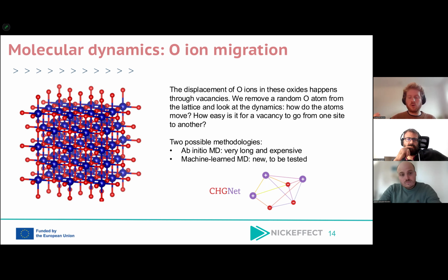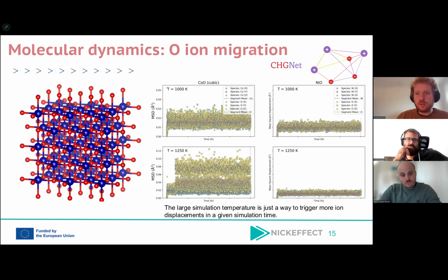Now there are many, many more different kinds of models. But so in CHGNet and in these other machine learning interatomic potentials, the forces are predicted using a machine learning model, and this model has been trained on DFT data. And so it's supposed to achieve close to DFT level accuracy, but at a fraction of the cost. So that's why it's very, very competitive and very attractive as a methodology. And so these are the results using CHGNet, so the machine learned interatomic potentials. On the left, it's cobalt oxide. On the right, it's nickel oxide.